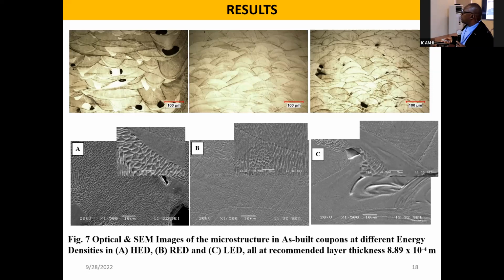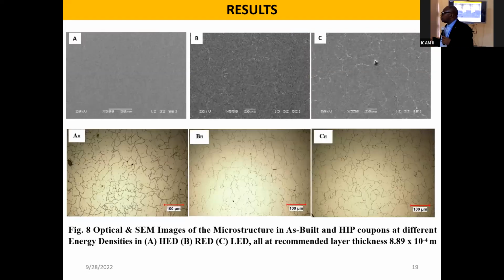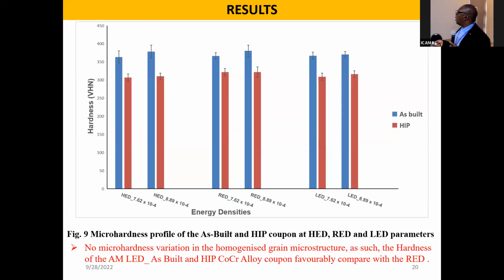But after heat treatment, you can see that the microstructure is essentially organized. There is no relation to whether it is low, medium or high energy density. So what is the summary from this investigation? We also look at the environment. This is as-built, and this is after heat treatment; there is organization and no relation whether using the material in as-built condition or after heat treatment.